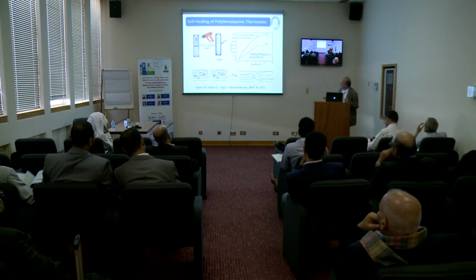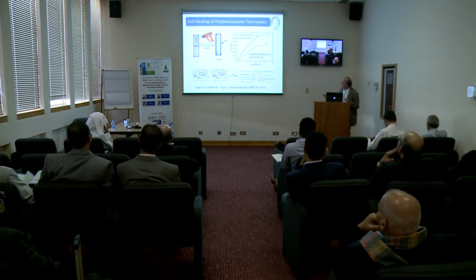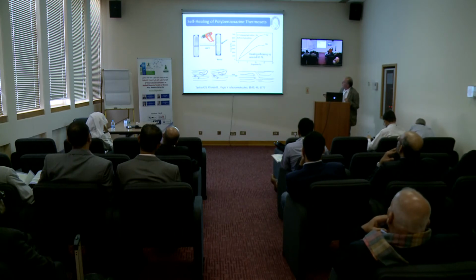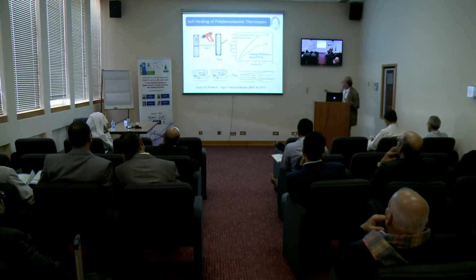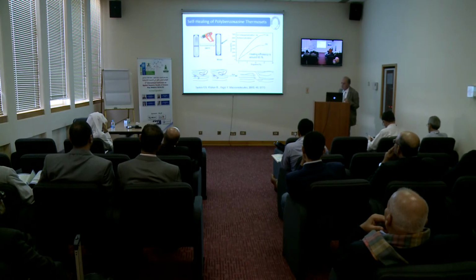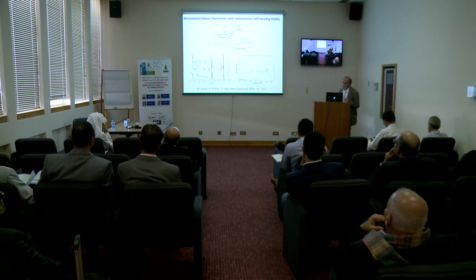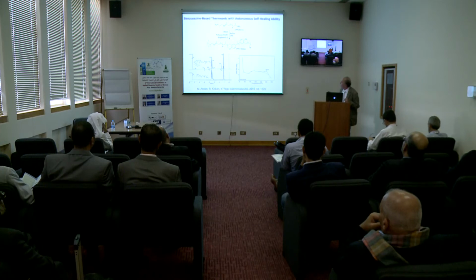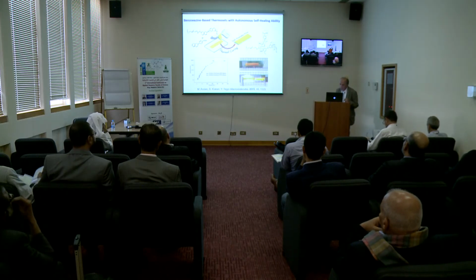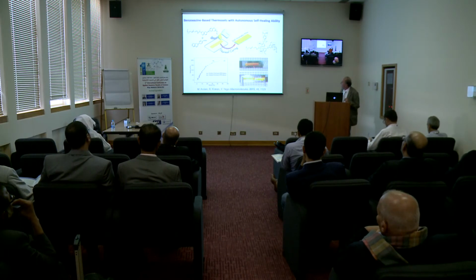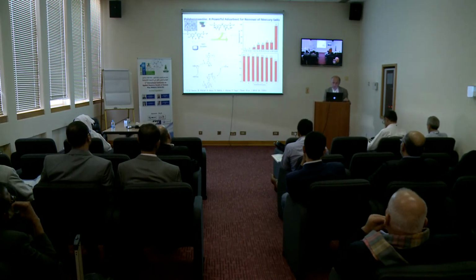In this case, we show that the material is cut. If you heat with a gun, you have a recovery here. As you see, the initial mechanical properties after healing is not exactly the same as before, but there is a 60% healing in the system. We have also kind of autonomous self-healing. In this case, we prepared main chain polybenzoxazine, I will show you the healing chemistry as well. We put on the surface here thermal curing, and after heating their self-healing material, this is linked together, and you can see it can be expanded, still strong, and it's a self-healed material.